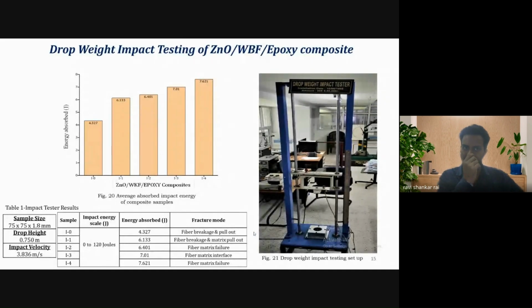After the preparation of the final sample, it was tested with drop weight impact testing of the ZnO woven basalt fiber epoxy composite. This is the setup of the drop weight impact tester. We kept the sample here and applied the impact load from a drop height of 0.75 meter with an impact velocity of 3.836 meter per second. The impact energy scale was 0 to 120 joule, for the different samples: the sample having no nanostructure, then 10 millimole, 30, 50, and 70. It was found that the 70 millimole structure has the highest energy absorption capacity due to the high amount of nanostructure along with the hexagonal nanostructure interlocking.